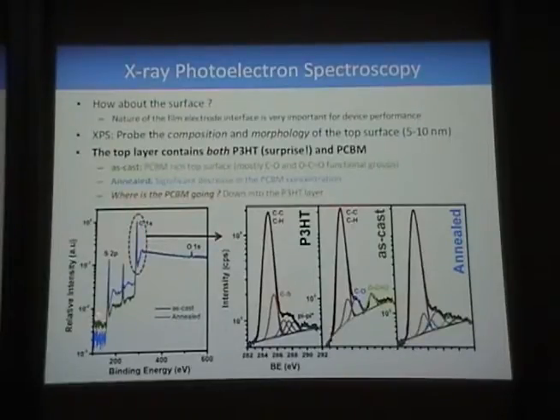So even in the as-cast, you can see that there is a small amount of P3HT on the top surface. And once you anneal it, as you can see in the blue trace, there's a significant decrease in the PCBM concentration because the sulfur peak rises quite considerably.